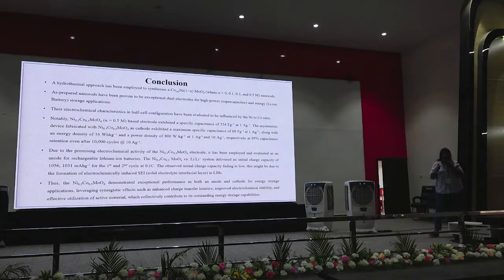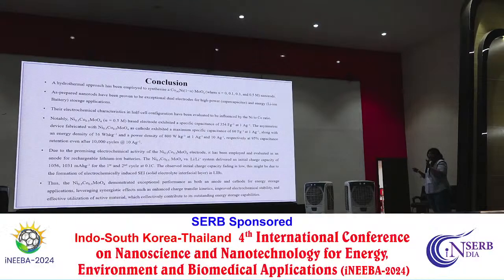The conclusion is that the same material has been used for both applications, supercapacitors and batteries, using the hydrothermal approach. For supercapacitors I've got around 300 farad per gram at 1 ampere per gram for the 3 electrode, and for the 2 electrode around 60 farad per gram at 1 ampere per gram. For the lithium ion battery I've got around 1000 for the first cycle and 900 at 1 C rate. Thus it demonstrates the same material can be used for both energy storage systems. Thank you.